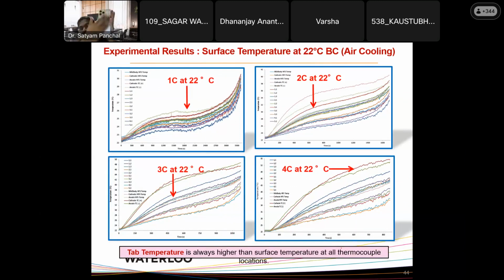As I said, ten thermocouples were pasted on the first surface of the battery, and then the average was taken. Here you can see 1C, which is 20 ampere at 22° ambient temperature. Then 2C means 40 ampere, 3C means 60 ampere, and 4C means 80 ampere constant current discharge. At 1C, the temperature increases from 22° to around 30°. But at the higher current, the temperature increases from 22° all the way to 50°.